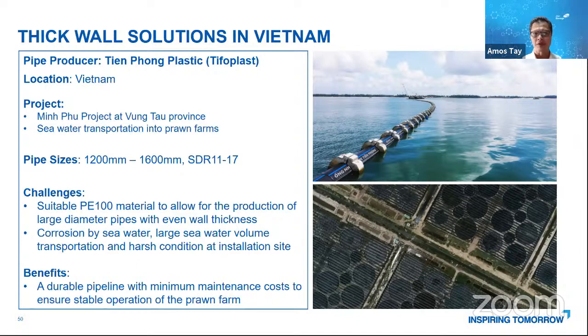And typical material will not be able to achieve this thick wall without a sagging phenomenon. So their challenge was to find a suitable PE100 material that allows the production of this large diameter and yet even wall thickness. Also, this material needs to be resistant to corrosion by the seawater because they are transporting seawater to the prawn farm, and need large volume. And you know other traditional pipes, maybe steel or ductile iron, will have encrustation, and then the pipe bore will become smaller. But with this PE pipe, the bore doesn't change.